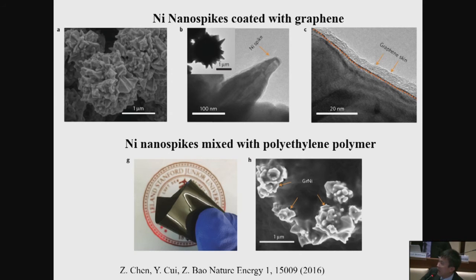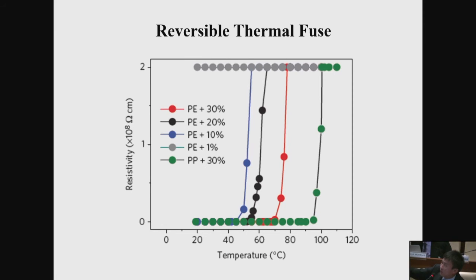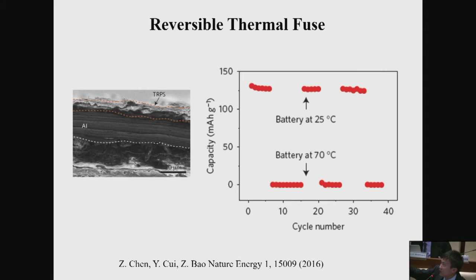Now you can see the key data: the resistance of this polymer film versus temperature. At room temperature it is a really good, metallic conductor. Then when the battery heats up, look at the green curve, to about 95 degrees C, there's a sharp transition, and this layer becomes a perfect insulator. The resistance changes by 8 orders of magnitude. So at this moment, the battery shuts itself down without releasing the electricity. You can prevent the bad things from happening. Here the battery is charging and discharging with capacity coming out. Once it heats up, you get to zero capacity. You cannot take the electrons out anymore. We need to do more testing. So far it's in the lab as a small battery cell. We need to do a big cell and a realistic cell for use in transportation.